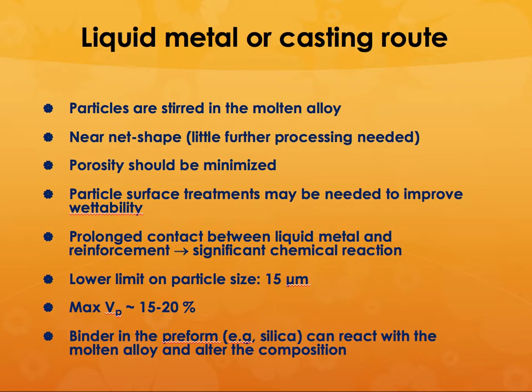and there is a maximum fiber volume fraction or particle fraction, which is about 15 to 20%, because otherwise you are going to end up with a lot of porosity. And if you have a binder in the preform such as silica, it can react with the molten alloy and alter the composition. So you have to make sure that these things don't happen.